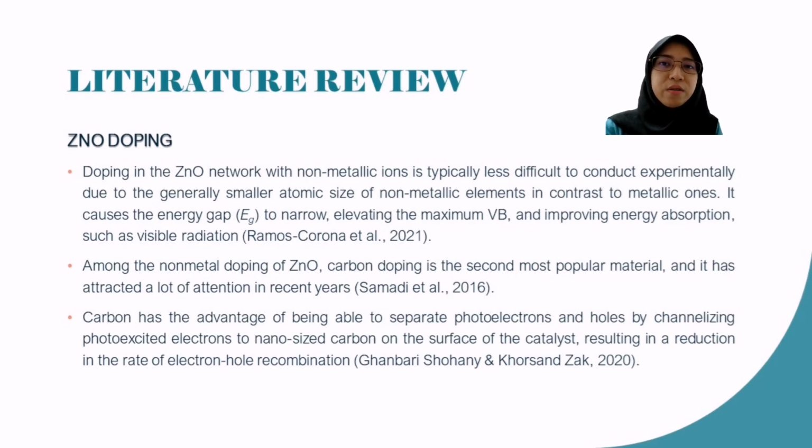Among the non-metal doping of zinc oxide, carbon doping is the second most popular material and it has attracted a lot of attention in recent years. Carbon has the advantage of being able to separate photoelectrons and holes by channelizing photoexcited electrons to nanosized carbon on the surface of the catalyst, resulting in a reduction in the rate of electron-hole recombination.